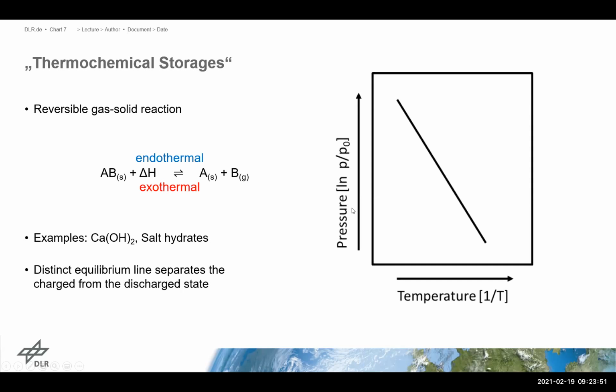Again, pressure, this is temperature. This is now 1 divided by temperature, so to the left is hot. But we have now only one single line. Or in other words, if we say we have a constant gas pressure available, we only need a slight increase or a slight decrease in temperature in order to reach full conversion, completely converting the whole material and thereby absorbing or releasing the maximum possible thermal energy.